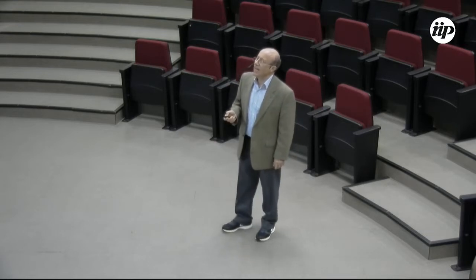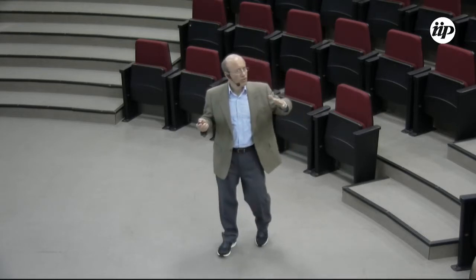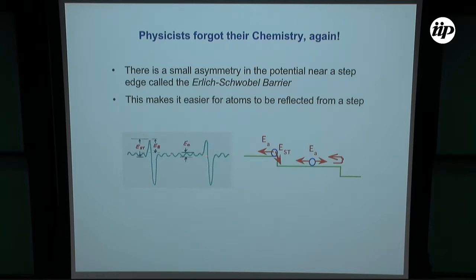Namely, that there is a small asymmetry in the potential near the step edge. As an atom approaches the step edge, the activation barrier all along the terrace is E_A, but as it approaches the edge, all of a sudden there's an additional step barrier in going down the step. So what that means is that if you calculate the probability for an atom to diffuse down a step or go back, there's a higher probability for the atom to go back on that terrace. This is a very small energy, like 0.03 electron volt compared to 0.3 electron volt, tens of times or hundreds of times smaller than the original activation energy.